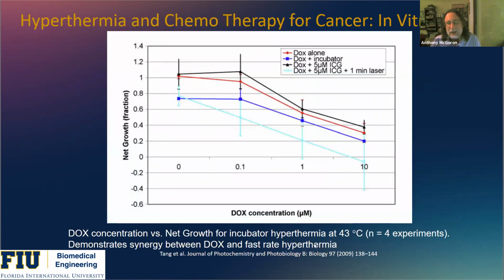This is a study that's more than 10 years old now that my graduate student did, in which we exposed cells to different treatments and at different concentrations of doxorubicin, which I'm sure you're familiar with as a chemotherapy agent, which had the expected dose response. If we add doxorubicin with 5 micromolar indocyanine green, the indocyanine green doesn't have any effect on the cells. If we put the cells in an incubator for this slow rate hyperthermia, we see the slow rate hyperthermia has some effect, and then adding the doxorubicin has an additional effect.